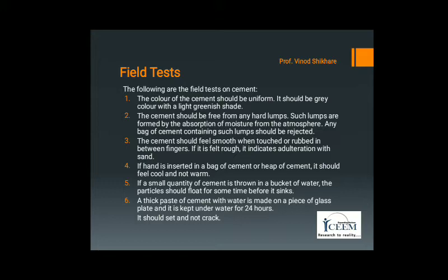If a small quantity of cement is thrown in a bucket of water, the particles should float for some time before they sink. A thick paste of cement with water is made on a piece of glass plate and it is kept under water for 24 hours. It should set and not crack.